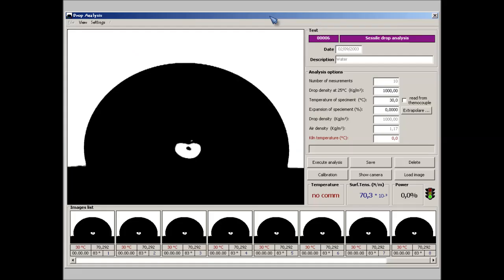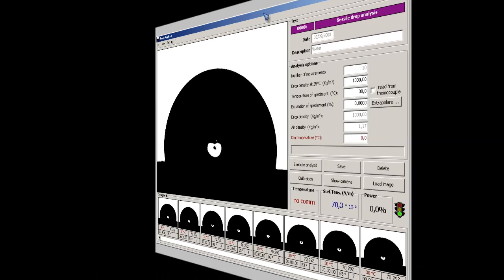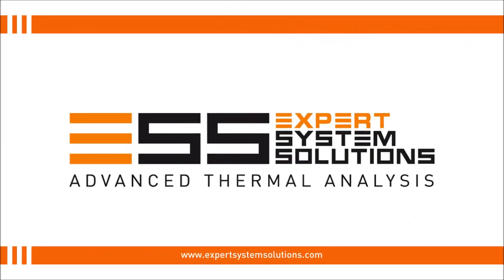This is the main window for the surface tension measurements. The shown example is the measurement of the surface tension on a drop of distilled water over a teflon plate at room temperature. The measured surface tension is 70.3 × 10^-3 N per meter and it is in perfect agreement with the values obtained on water with all the other methods.